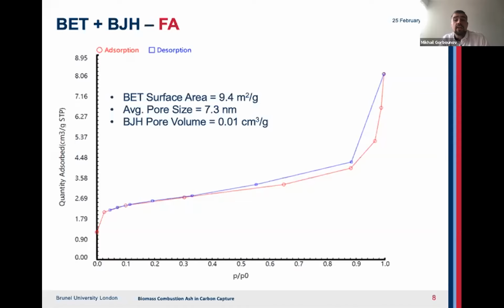In contrast, the BJH cumulative pore volume is calculated to be about 0.01 cubic centimeter per gram, which is well within the reported range for ashes, both biomass and coal. The average pore diameter is estimated at about 7.3 nanometers, which is consistent with the IUPAC technical report, which specifies that for type 4 isotherms, hysteresis occurs if the pores are wider than 4 nanometers, and if the tests are conducted under nitrogen and 77 Kelvin, which they were. And the difference between the adsorption and desorption pattern is clearly identifiable from the slide.